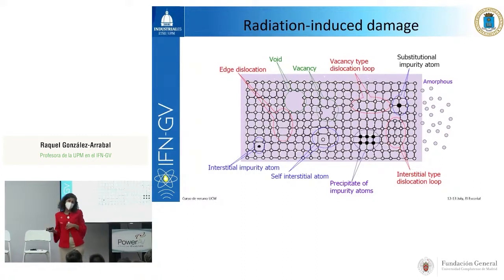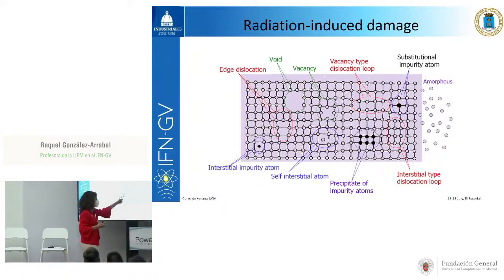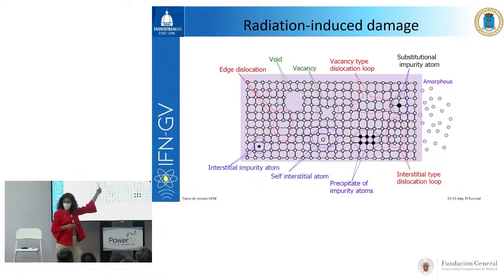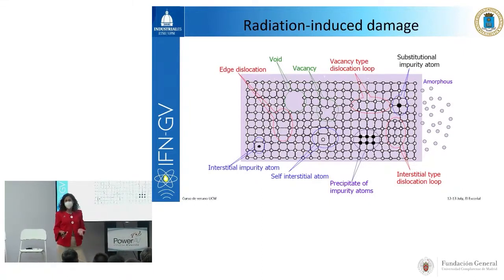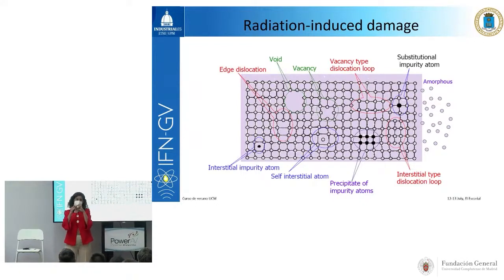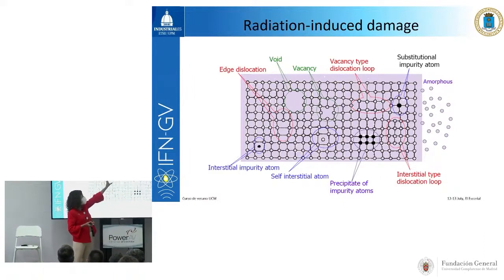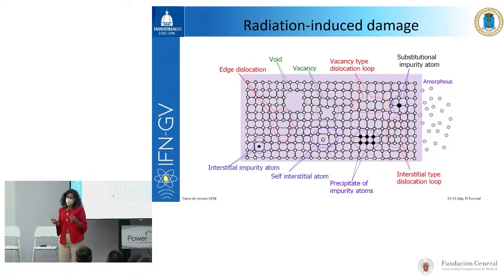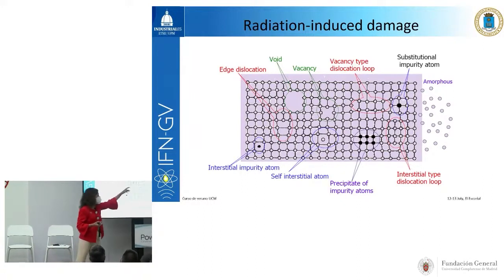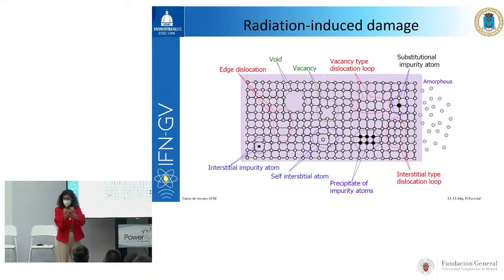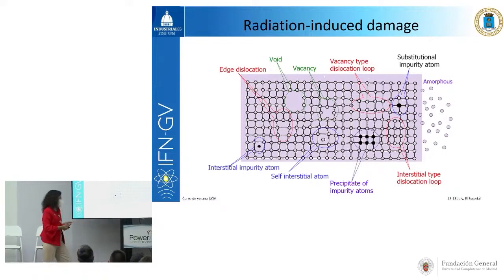But vacancies and interstitials are mobile, so we can have clusters of vacancies. So we may have voids, really voids. And at the same time, we have voids and we have gases. So we have helium, we have hydrogen, and its isotopes. What is going to happen is that the gases are going to come to these voids and form bubbles. And when the helium or hydrogen content is large enough, these bubbles are going to be overpressurized, and then finally the material is going to crack.